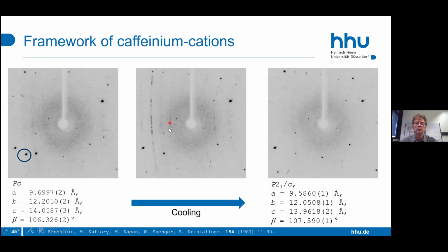So in this middle image, you see that some reflections stay the same. They are stable, mostly affected by the framework that doesn't change. But some reflections are heavily involved in the phase transition, this reorganization of the I3- within the channels. And at the end, you see that reflections even disappear and we come to this higher symmetric polyiodide structure. In my working lifetime, it's the first time I ever see such a thing, looking into the crystal and really seeing the phase transition. I was really happy about this. And it's also still not published.